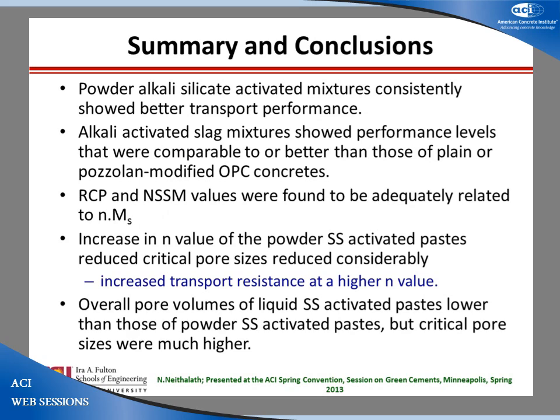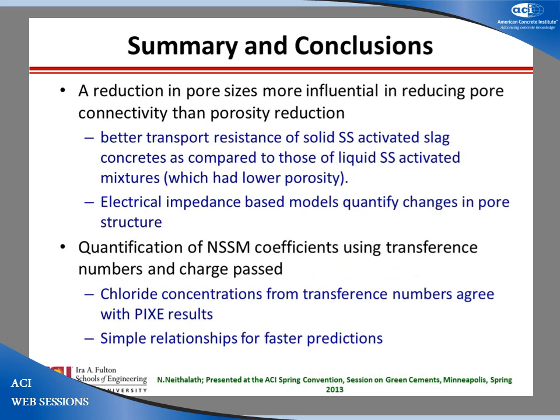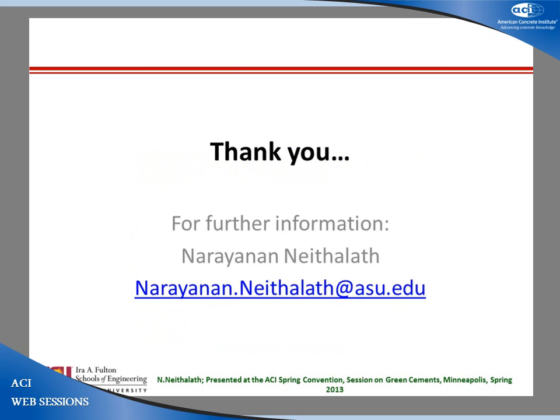So just to summarize, I'm not going to go through all of that. Powder mixes consistently showed better transport performance, comparable or better performance for all these mixes compared to OPC concretes. Overall pore volume effects, which we talked about. One more: reduction in pore size is more influential in reducing pore connectivity, and quantification using the results that I showed, faster predictions. Thank you very much. I think I'm on time. If you have any questions.